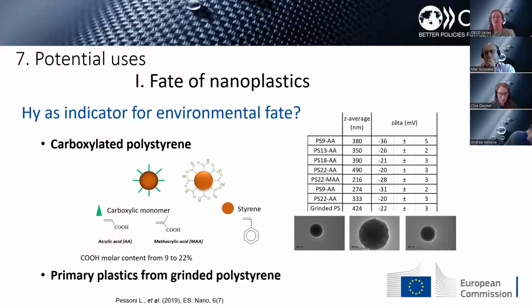Here we tested particles based on carboxylated polystyrene with different molar concentrations of carboxylic monomer. Two types of monomer were used for the synthesis, and we wanted to assess the effect of the type of monomer as well as the molar content used in the synthesis. We also tested primary nanoplastics obtained from grinded polystyrene.